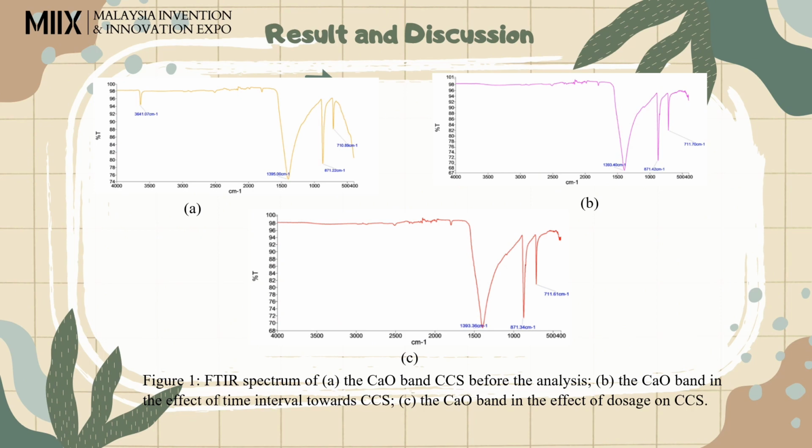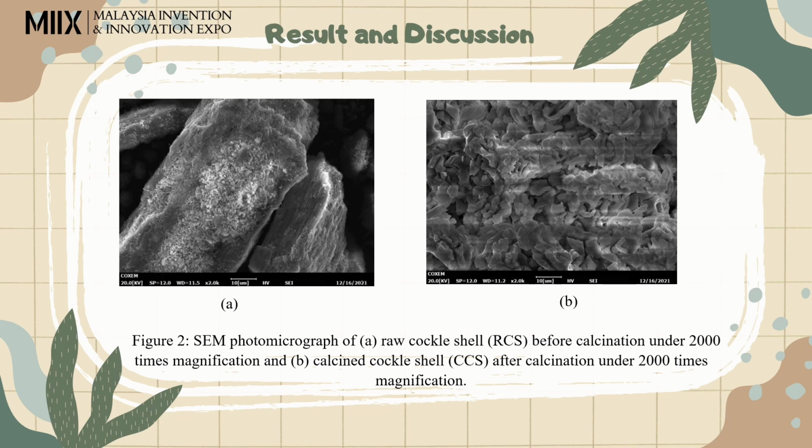The difference between the three spectra was the observation of a new peak on the calcined cockle shell absorption spectrum at 3641.07 cm⁻¹. Scanning electron microscopy, SEM, was used to observe the surface morphology of raw cockle shell, RCS, and calcined